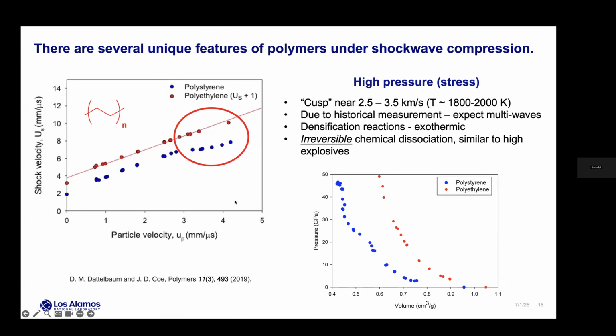And one thing to note about this is that it's irreversible. So as a chemist, you know this, right? But when you think about the shock physics related to this, let's say you shock above this transition, and you were to send a release wave through the material or a second shock, your wave speeds are going to be incorrect unless you measure this, unless you model this irreversible chemical dissociation.